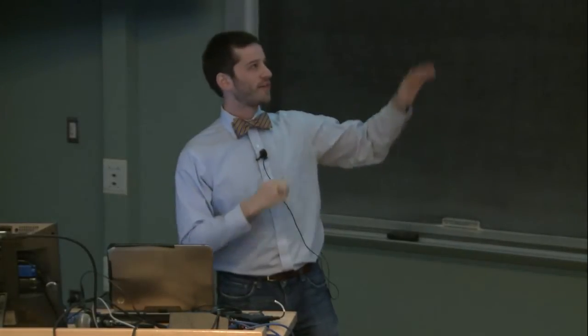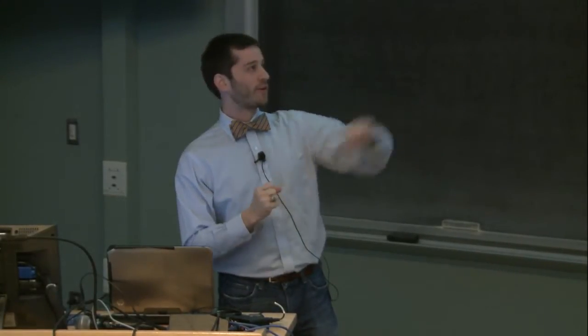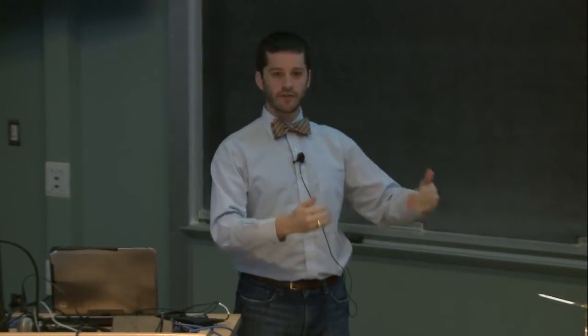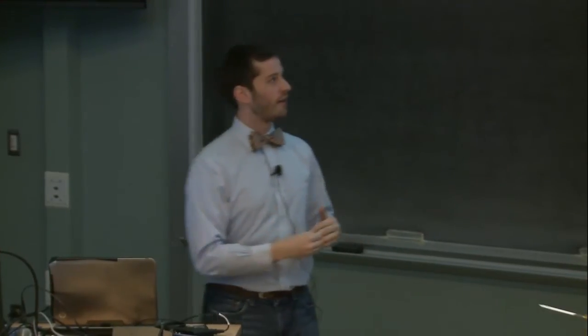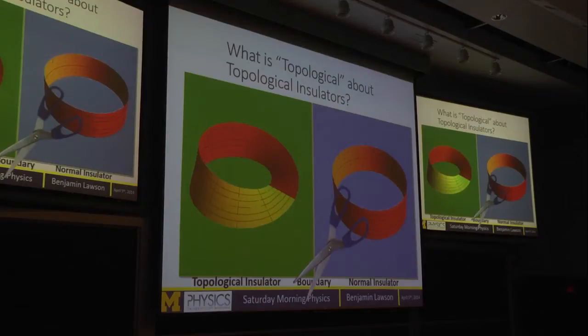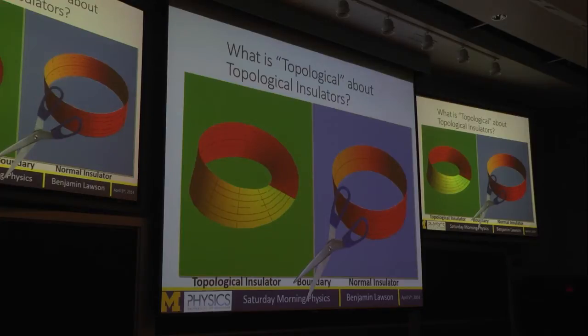The quantum property inside these materials is like a Möbius strip or like a loop. If I were to smoothly transition out of the topological insulator into the normal insulator, there's a break in the topology. Along the surface, I have to basically tear this quantum property and re-glue it back to itself. This allows there to be surface states — conducting electrons along the surface of the topological insulator, but only along the surface. That conductance comes out of this breaking in the topology.